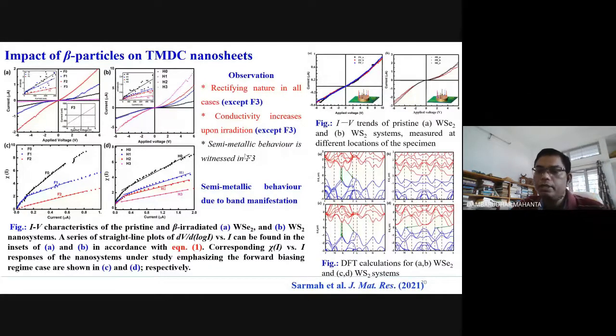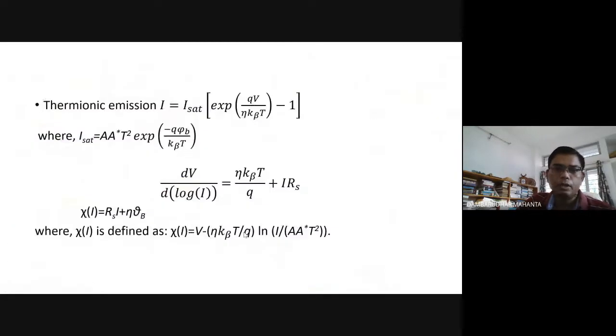So in that regard, we have considered DFT calculations and found that in the first upper panel for the WSe2 system, when sulfur vacancies are more, there is an overlapping of the top of the valence band and the bottom of the conduction band. So that is probably why it is not showing a rectifying contact. In other cases it was semiconducting. It means that in this particular work we have mentioned that there can be a possibility of converting a semiconducting material to semi-metallic behavior. Some of the equations we have used and measured different parameters using thermionic emissions, etc.